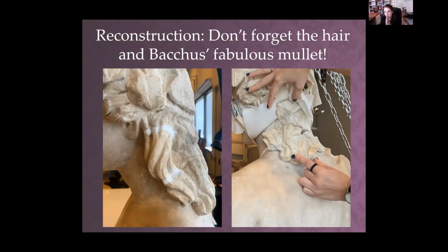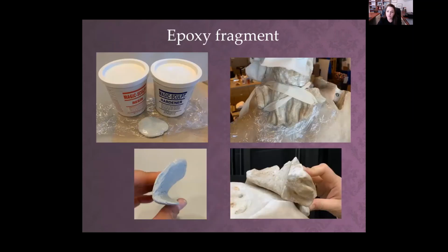So the mullet is actually an important piece structurally. Remember, the head is from Thasos, the island in the north of the Aegean. The torso is from Turkey, and the mullet is probably Carrara, so from Italy. Most likely it's post-antique, but it is a wonderful triangle piece. So you see here in the lower right corner, it's a triangle of stone that fits into a loss where the head and the body come together. And it's very structurally important because it locks the head into place. Because it was carved from a different piece of stone, the joint is not perfect.